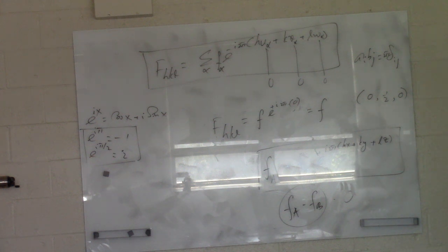Because diamond also FCC, right? That means it should follow that FCC thing, but there are some additional features you have to satisfy. By looking at this one, you can say, just like before, all odd, all even, that situation is true, but important thing is, in the diamond case, the sum of these 3 should be a multiple of 4.